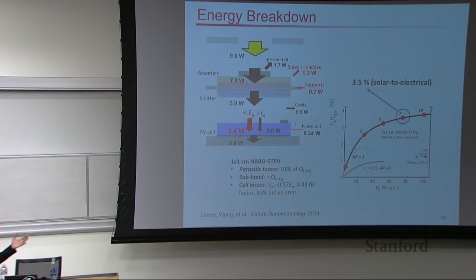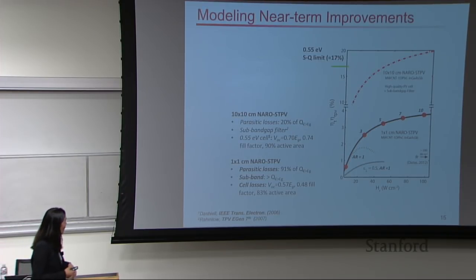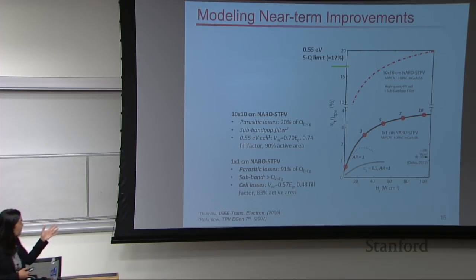And so what we've started to do is think about, given the device that we have, how do we take advantage of the energies below the band gap that are not useful for the conversion process itself? Part of this process is also modeling and thinking about what is possible if we were to scale up and improve some of these device designs based on the understanding that we've obtained. You can see here that if we go from a 1 by 1 centimeter STPV device that I just showed you to about a 10 by 10 centimeter device, you have significant potential to even exceed the Shockley-Queisser limit of these low band gap cells.